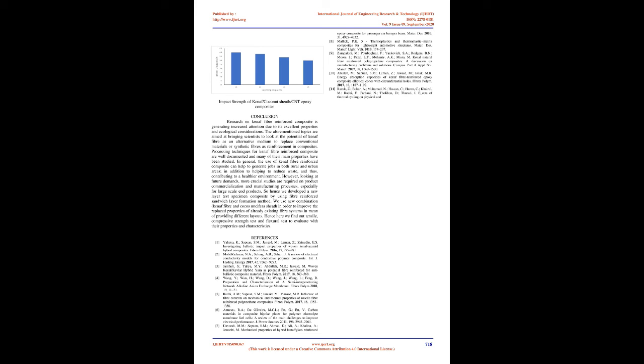This is because the tensile properties of Kenaf single fiber are much higher than the Cocos Nucifera Sheath single fiber. Replacement of Kenaf with 25 weight% of Cocos Nucifera Sheath, L2, reduces the tensile strength by only 5%. Similar results were observed in case of tensile modulus. Hence, the high-performance non-available Kenaf fiber can be replaced with naturally woven agro waste, coconut sheath, for non-load bearing applications such as automotive and aircraft interior components.